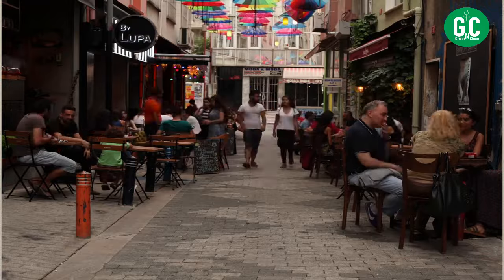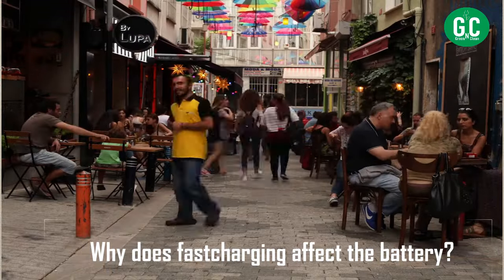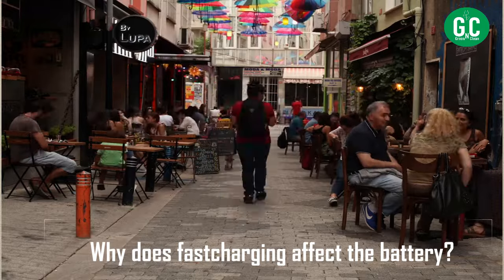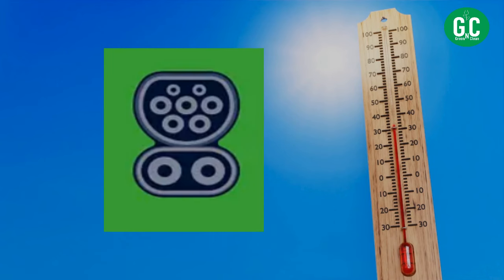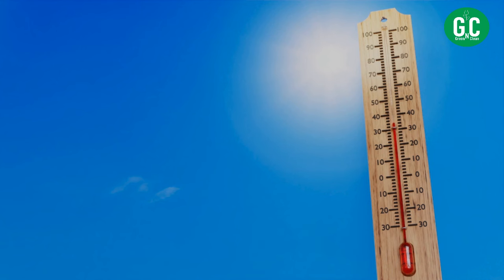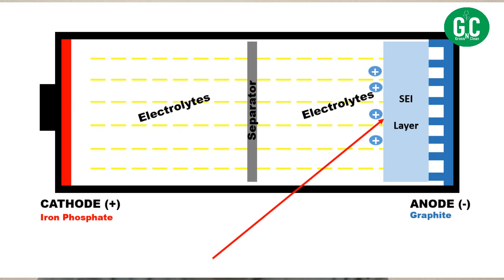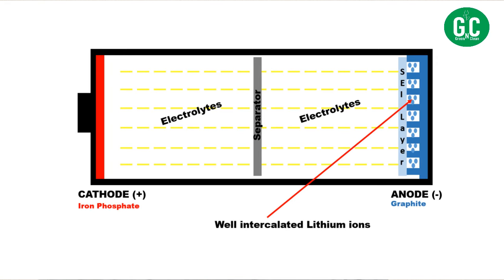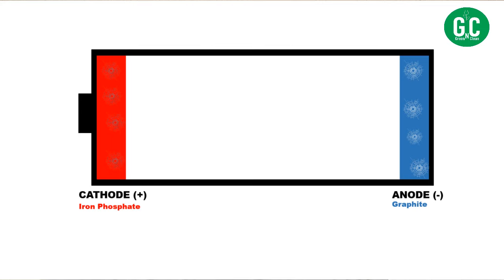Now, how does fast charging degrade the battery faster than slow charging? The number one enemy of the battery is temperature, and when you do DC fast charging, the battery undergoes a higher temperature when compared to slow AC charging. And when the temperature is high, you are causing SEI layer formation. You are also accelerating the lithium plating. So everything that I said, the degradation of the materials in the cathode and anode, they all happen faster because the battery is under tremendous stress when you do fast charging.